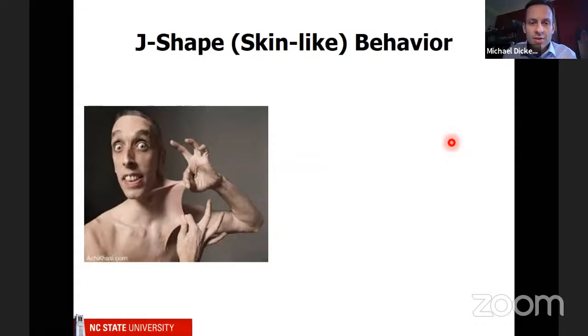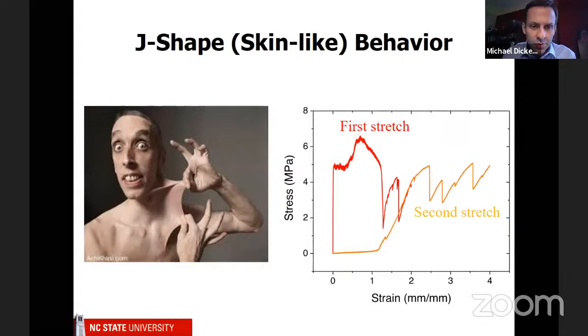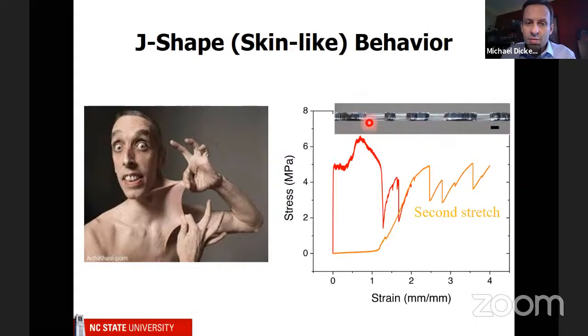And so we can actually do this. When we make our first stretch, it's actually stiff. So this is not good. But then it breaks, and then it breaks again. So then if we take the thing and we stretch it a second time, because we already have these breaks, the second time it will actually look like a J, this orange data. It will be very easy to stretch, and then it gets much, much stiffer.